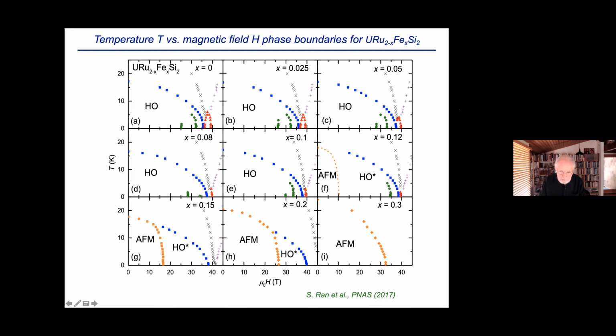And so you can see this more clearly at higher concentrations. So here is antiferromagnetism in this region, hidden order over here. And then again, this is the line delineating the coherent region over here in the non-Fermi liquid region, and then the Fermi liquid over here, and so on and so forth until at some point you only find the antiferromagnetism. So that's basically the way it looks.